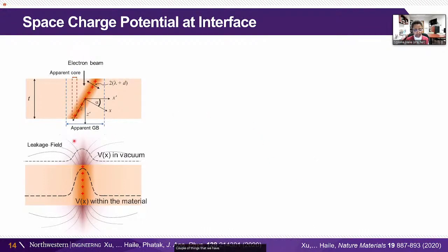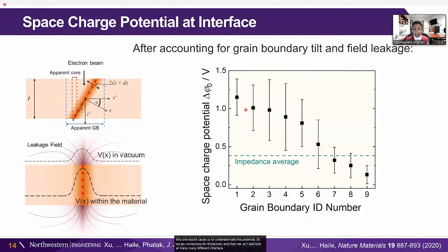A couple of things that we have to correct for. One is that the electron beam may not be exactly parallel to the grain boundary. The second is that there is a little bit of leakage of the electric field into the vacuum, which would overestimate the potential. This one would cause us to underestimate the potential. So we do corrections for those two. And then, as I said, we look at many, many different interfaces. And what we can see is there is indeed a wide range of the space charge potential. That's the value right at the interface. So that's the peak value of that voltage. And it spans from over 1 volt down. In some cases, we saw interfaces that had no voltage associated with them at all. It's quite a remarkable range.